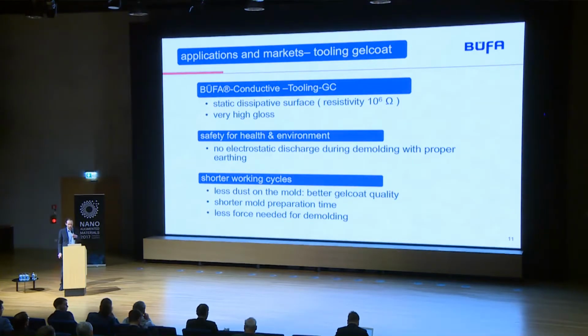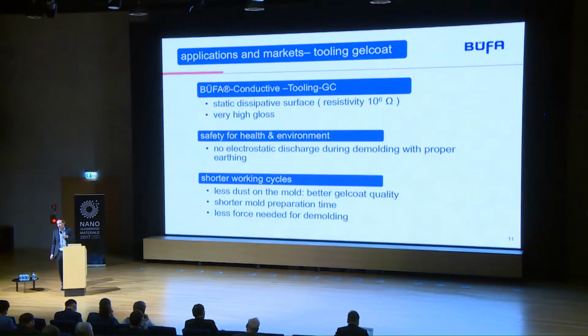Another benefit we found is for our customers with shorter working cycles. You have less dust on the mold. If you demold, you have the electrical charge on the surface, and every dust you have in your production site goes directly to the mold, and it's sometimes really sticky on the surface. With the new tooling gel coat, you have no charge on the surface, so you have less dust on your surface. And this means directly better gel coat quality.